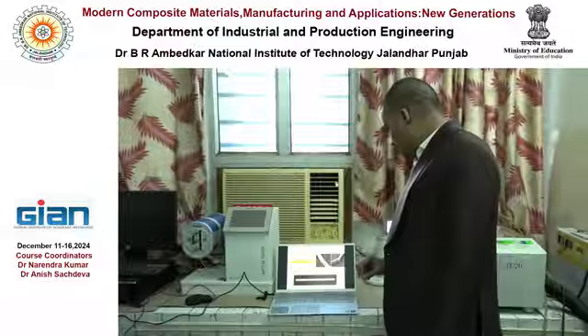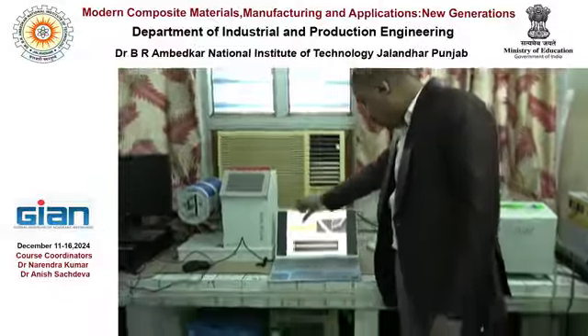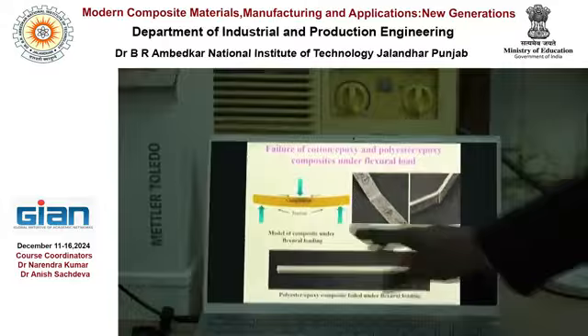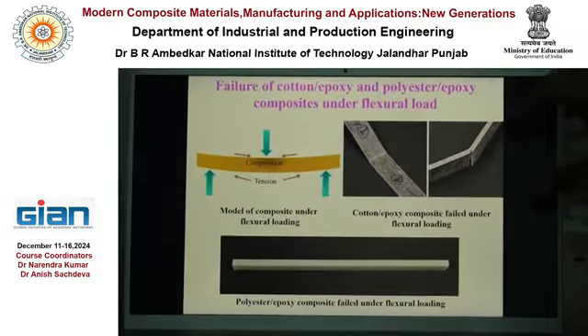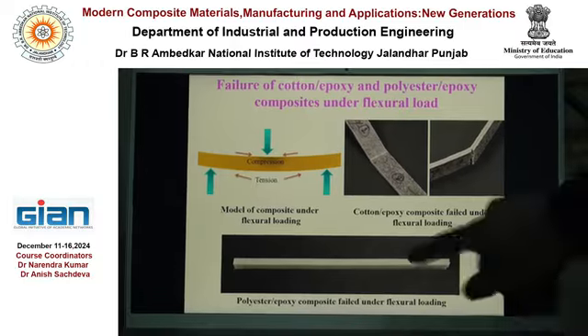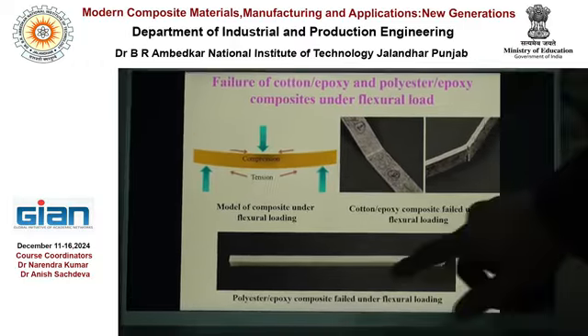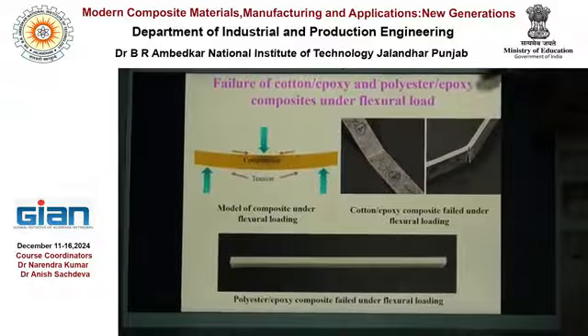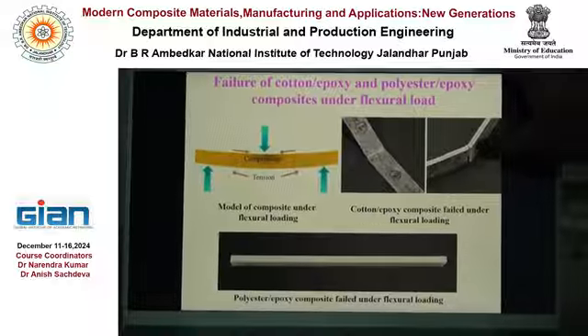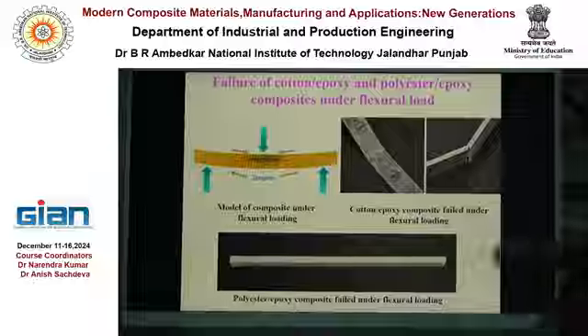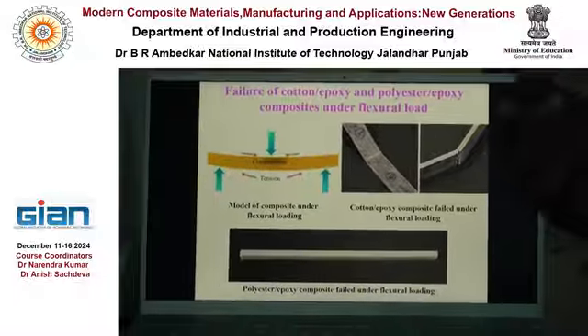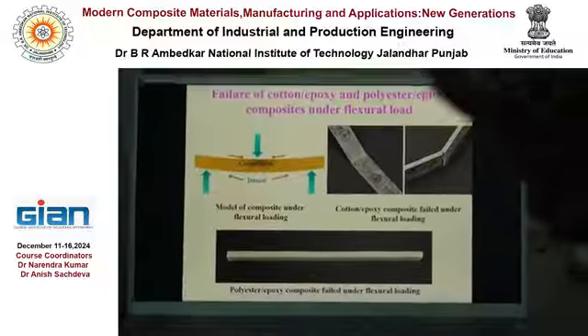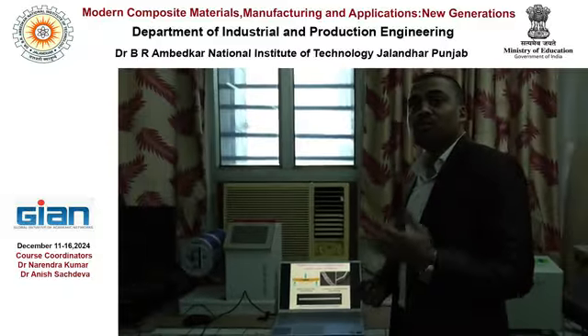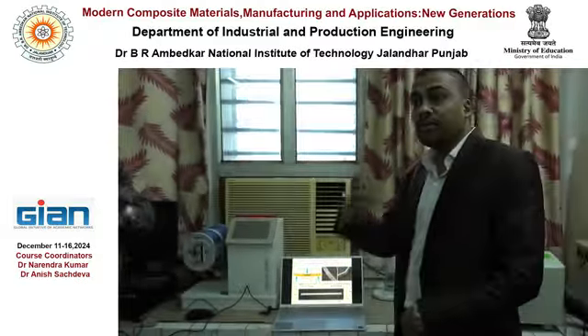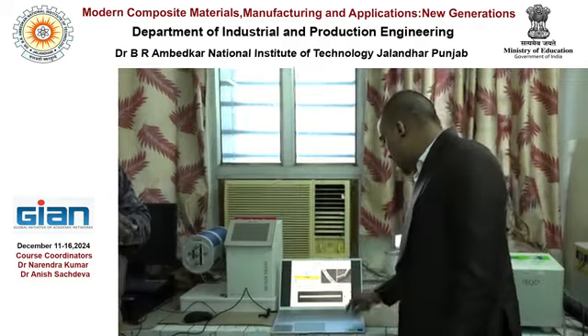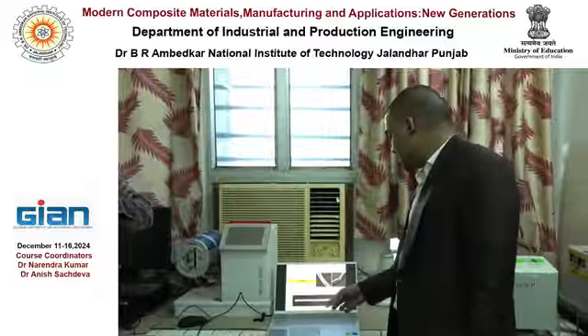Under flexural tests, for example, as I said, under 3-point bending, the top layer experiences compression and the bottom layer experiences tensile load. If you look at this composite material, this is the recycled cotton epoxy and this is the recycled polyester epoxy. You see that in the cotton epoxy composite, you can see the fracture of the material at the tension side, but in case of polyester there is no fracture. The reason behind this is that polyester is more flexible. It has more elongation at break, more than 20% elongation at break. Polyester fiber sometimes has that, so the composite material gets more elongation at break, and therefore